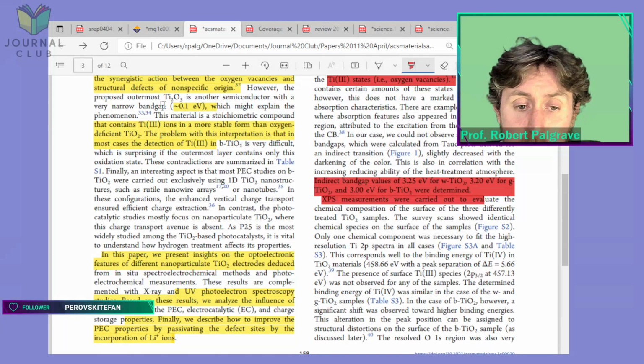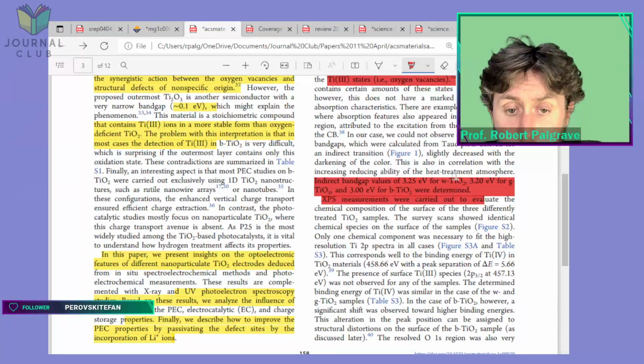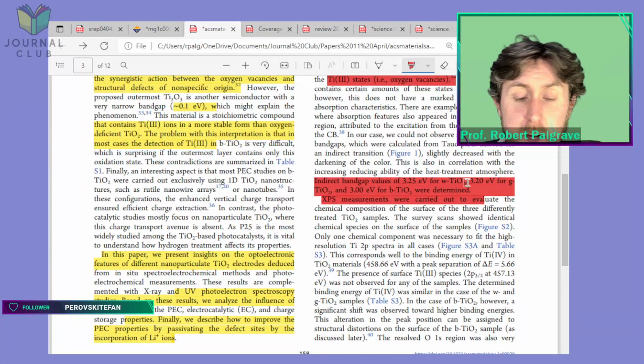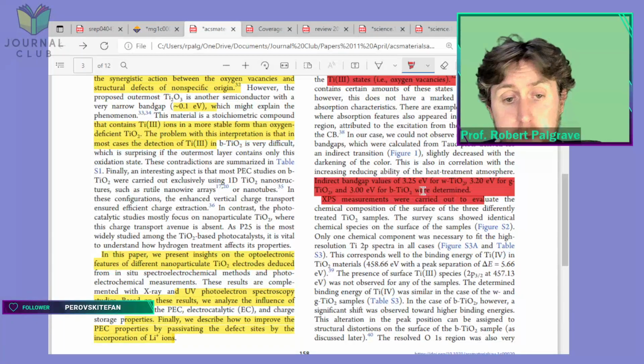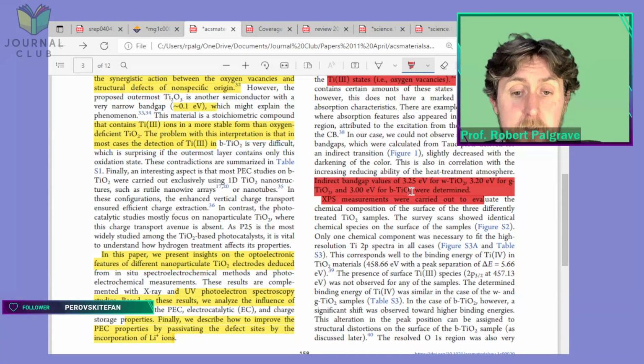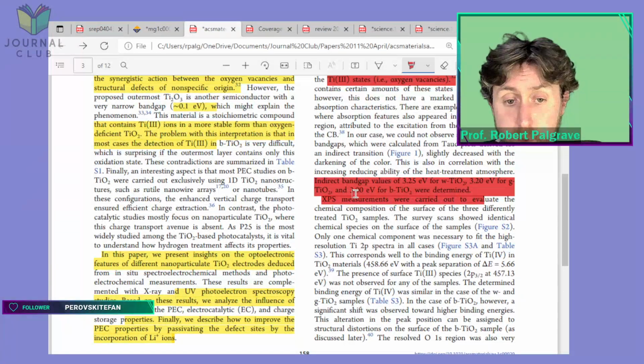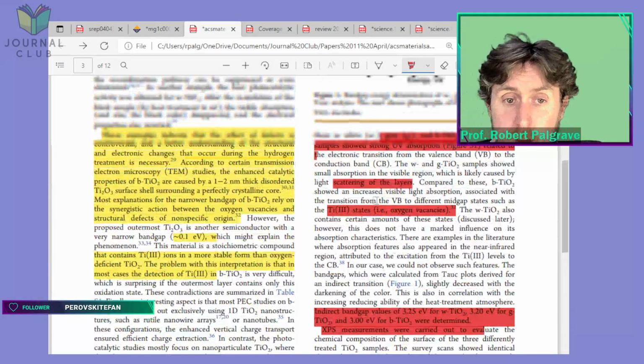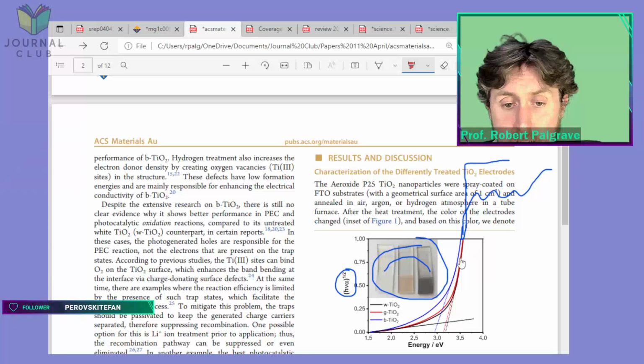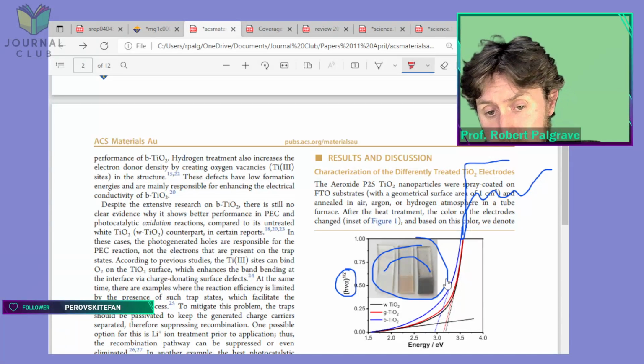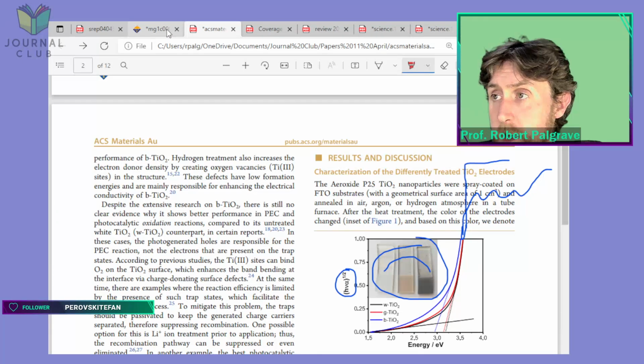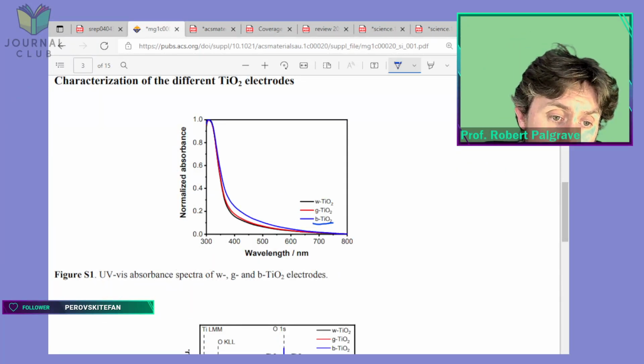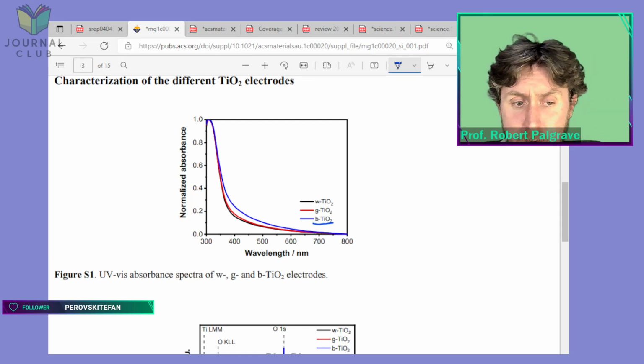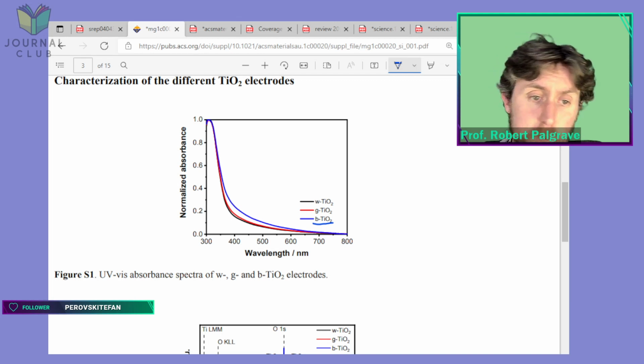But anyway, they came up with these values of 3.25 electron volts for white TiO2, 3.2 electron volts for grey TiO2, which is kind of normal for anatase. P25 is largely anatase phase, and black TiO2 is 3 electron volts, so it's a little bit smaller. Again, I think it depends exactly how you do this linear extrapolation. If you extrapolate this absorption edge down here, I think you would expect very, very similar numbers from these three. So it's difficult to determine exactly.